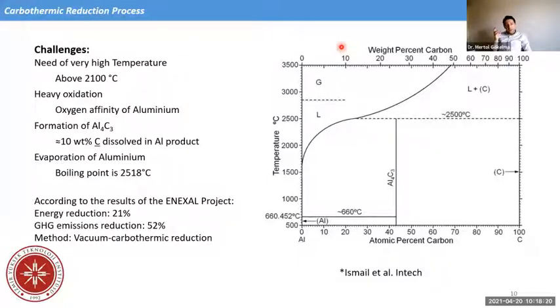But when we have the solid aluminium product and it cools down, the solubility will decrease, so aluminium carbide will precipitate. And with 10 weight percent carbon, for every 3 carbon you see here, you need 4 aluminium. And as far as I remember, there will be approximately 1.5 times more aluminium carbide at the end in the product. So that means something between 10 and 15% aluminium carbide you will produce in aluminium production. If nothing oxidizes, the yield will be 75%. If there is also some oxidation, it can dramatically reduce the efficiency.